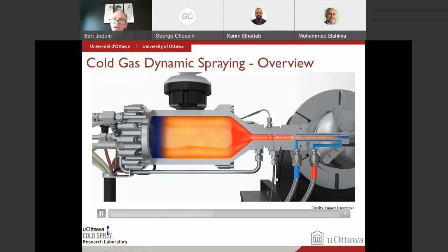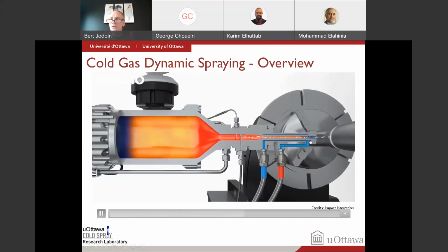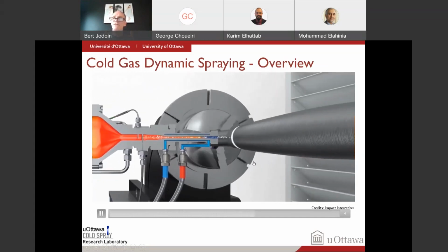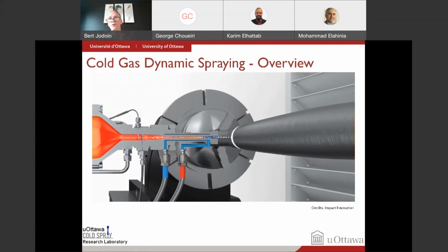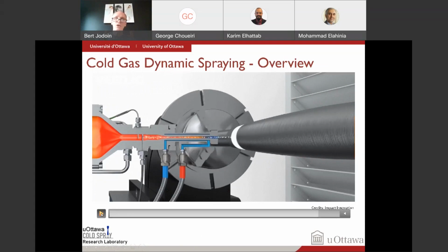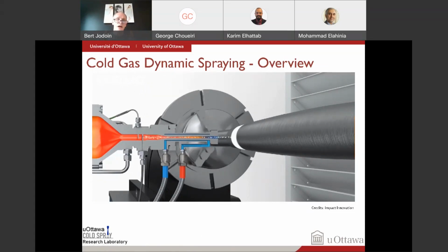Then we inject here our tiny powders, the tiny micron-sized powder. They're injected in this converging, diverging nozzle. They're accelerated to a high speed sufficient to not bounce off, but rather stick. And then if you move the gun or the part that you're trying to coat, you're going to create what we've seen before. You're going to create a coating. So this is how we do it in the lab. This is how the cold gas dynamic spray process does work.